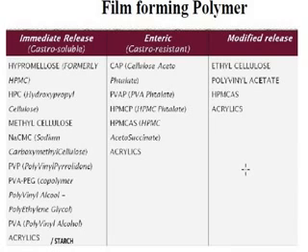Then another particular type of polymers is used for modification of release. We use them to release your tablet in a particular manner, called sustained release or controlled release pattern. So ethyl cellulose, polyvinyl acetate, HPMC grades, acrylic polymers, Eudragit RS100, RL100. There are various types of new polymers. Generally, they are used to coat your tablet to obtain modified release of the tablet.